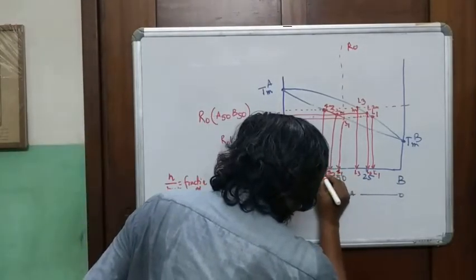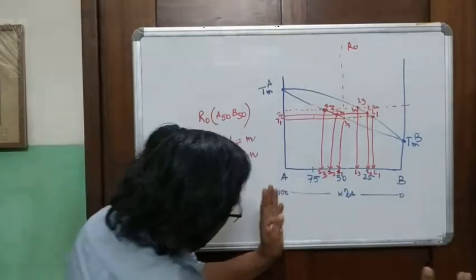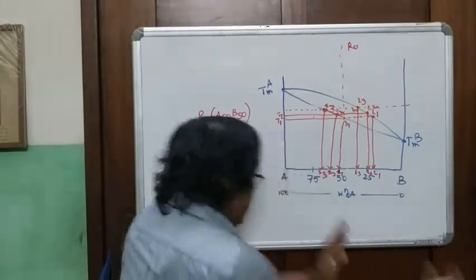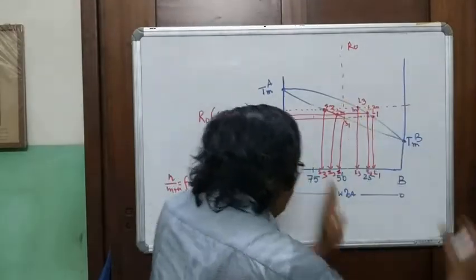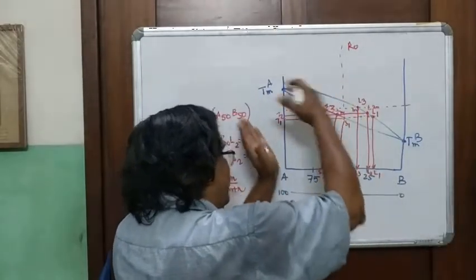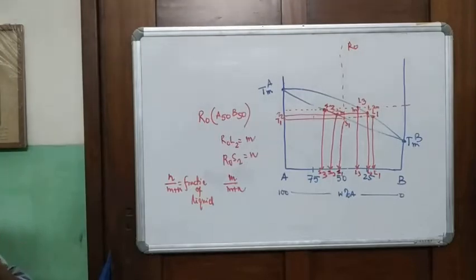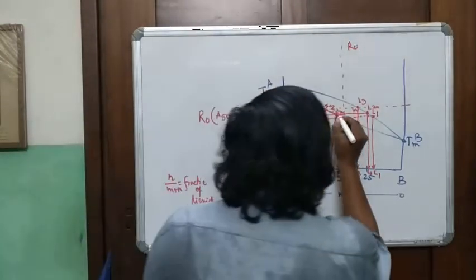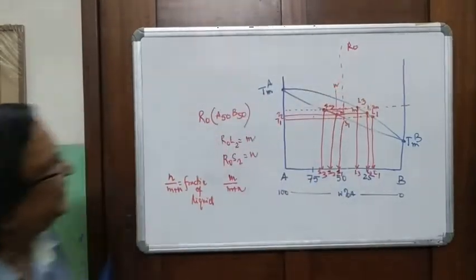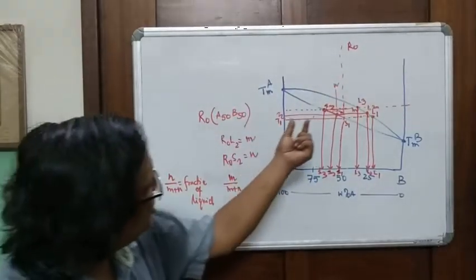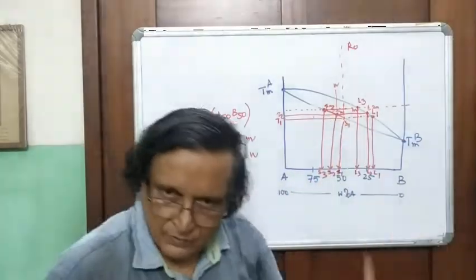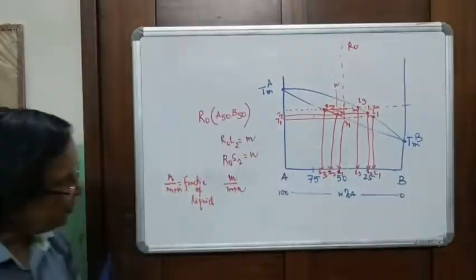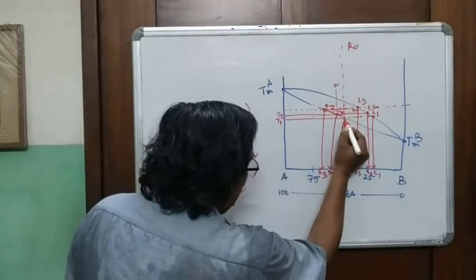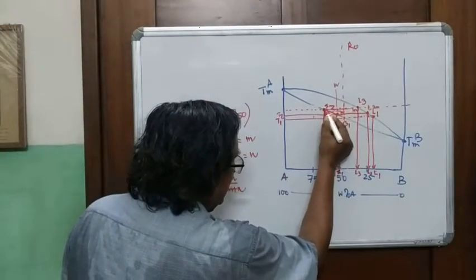And this is S1, S2, S3. So you see, from L1 to L3 and S1 through S3, the whole material is becoming richer in A. And you can see at this point, this is now where your N is. This is N. Can you see? Now the fraction of N is increasing. Have you understood? So here at S1, N was 0. This was N1. Now it's N3.